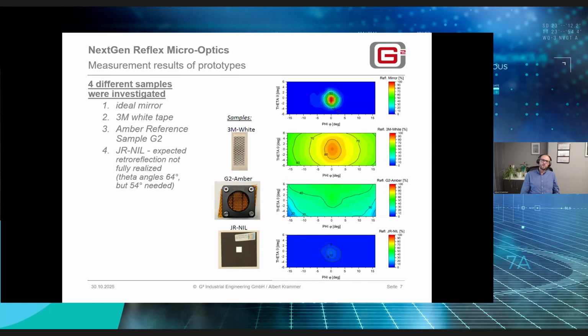So this is probably the most interesting slide for the optical engineers in the participant list, the measurements. Yeah, for an ideal comparison, we took an ideal mirror here. You can see the results here on the right top picture, where you can see close to 100% reflectance in the center zone at 0 degree vertical and 0 degree horizontal.